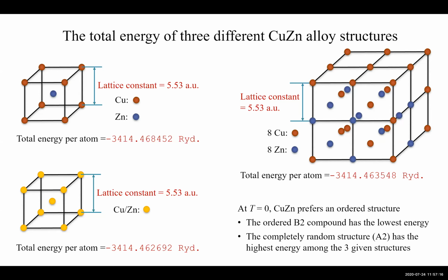That's something I did with a postdoc of mine a few years ago. If you just do this, though, you have to be aware that these types of calculation still neglect the phonon contribution to the entropy, which would account for the remaining 100 Kelvin or so in the transition temperature.